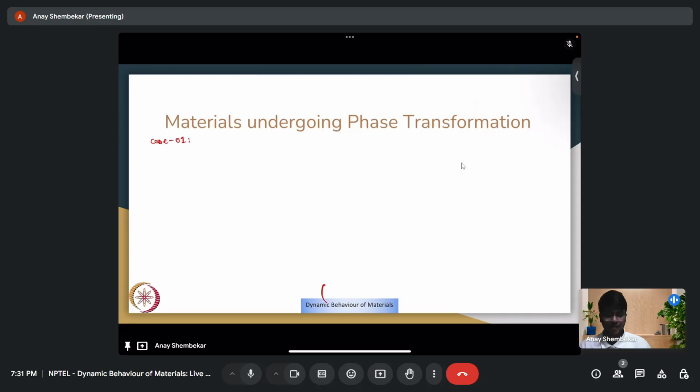First, the very first reported, which is an alpha to epsilon phase transformation in iron seen at 12.8 GPa. So very high pressure, 12.8 GPa, and the phase transformation is seen. So before that, we first need to plot a unary phase diagram. Unary meaning one component. A phase diagram is basically the different phases involved at different degrees of freedom.